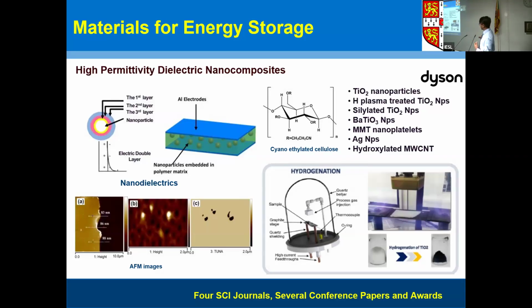And you can see this AFM image, how small in terms of thickness, less than even 100 nanometers. Those are the dielectric thin films. You can have those nanoparticles embedded within the system, and you can see how charge dissipates. For any material there is at least nanoscale, picoscale leakage current, so you can even trace out those leakage patterns as well. So that was my PhD project, and this was funded by Dyson at the Cambridge University Engineering Department.